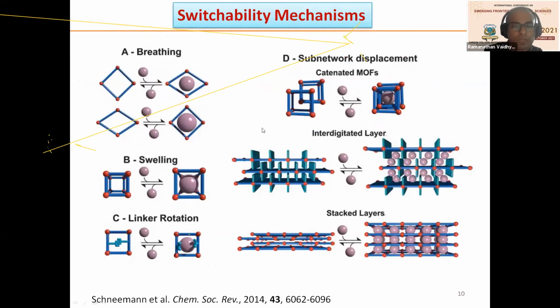Now, you can see a variety of structural changes that are possible in a MOF. One of them I explained already, breathing. Another one is called swelling. Uniformly, the MOF expands in all directions, like a sponge which swells up after absorbing water. And then another very interesting one is linker rotation. If there are linkers present in the MOF, which is the organic part of a MOF, they can rotate and reorient themselves so that openness is created in the MOF. So a MOF which was impermeable to a gas molecule can become permeable after this molecular structural change happens.